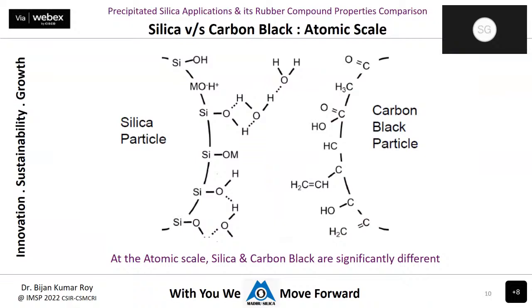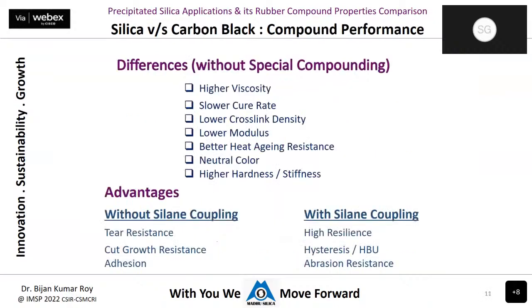Now, due to these differences between carbon black and silica, silica compounding gives a higher viscosity, the rate of cure will be slower, and lower crosslink density. But again, when we're talking about silica compound in rubber, because in rubber there are basically 3-4 types of rubber, like styrene butadiene rubber, butadiene rubber or natural rubber, mostly used in tires. Silica, being polar in nature, is not that compatible with the polymer itself. So when we're using silica in higher dosages, there is another requirement, a silane coupling agent, required to mix all the silica into the rubber matrix. So with a silica-silane system, all the required properties will be achieved. That is high resilience, low hysteresis, and better adhesion. That is the better durability of the tire.